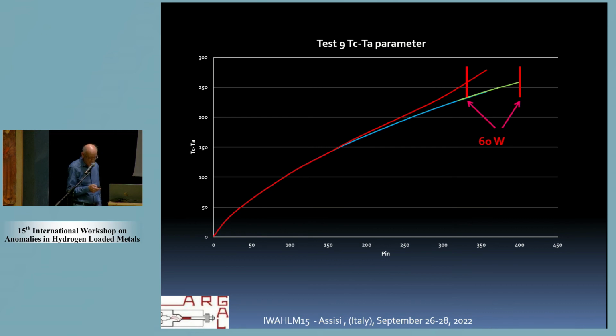For the same test, I said that the temperature of the reactor doesn't follow in terms of extra heat and extra power the same value we have outside the reactor, because there is dispersion inside the volume of the reactor to the edge of the reactor itself. So here we can estimate about 60 watts from the temperature of the reactor.